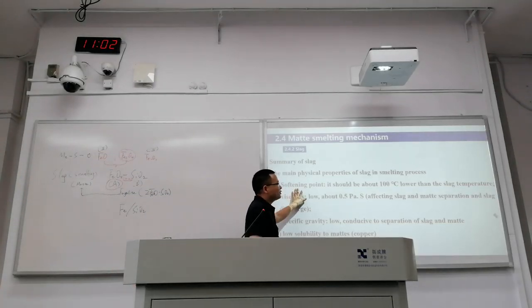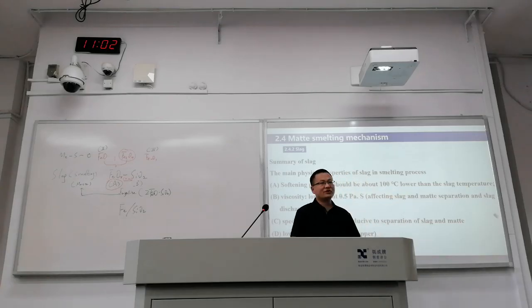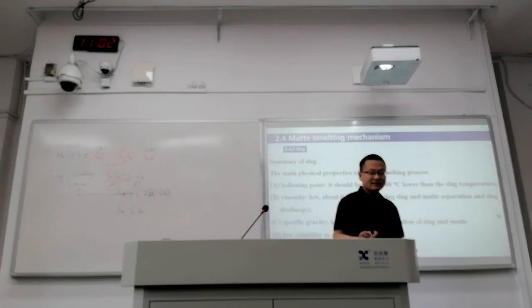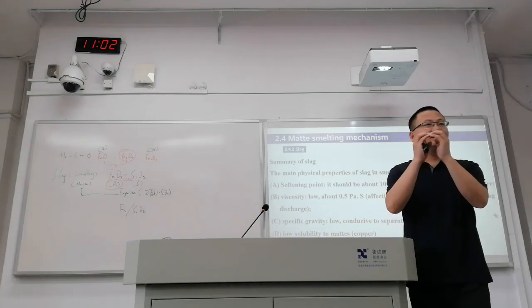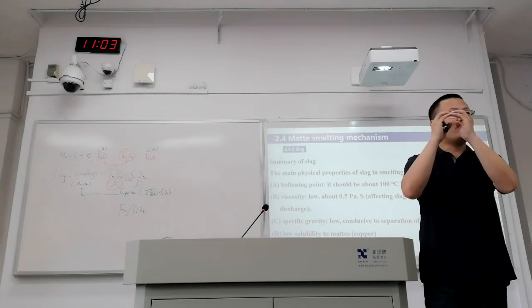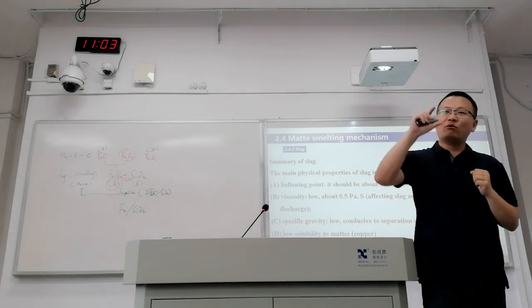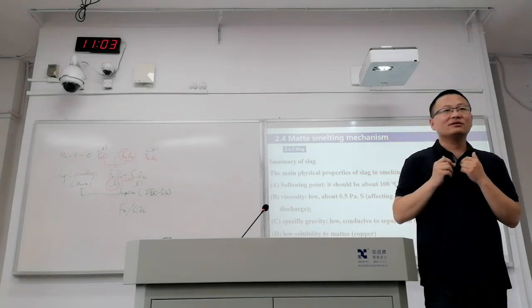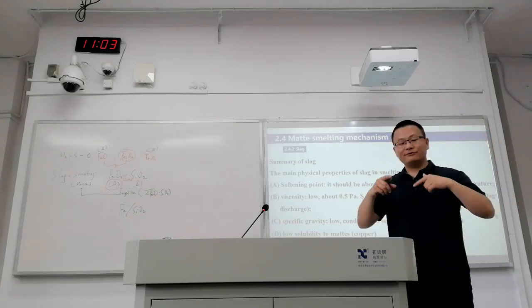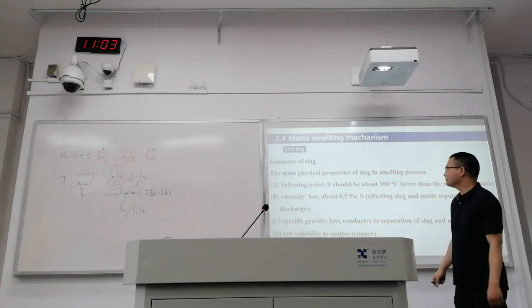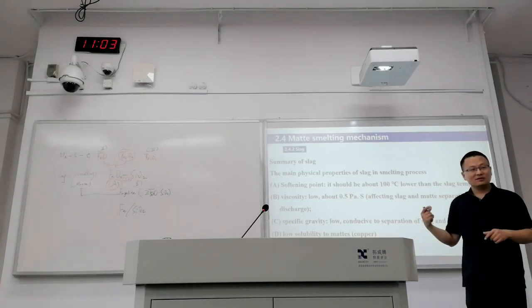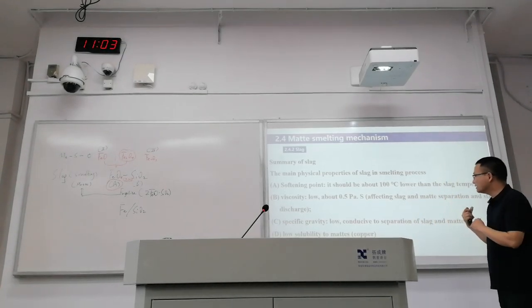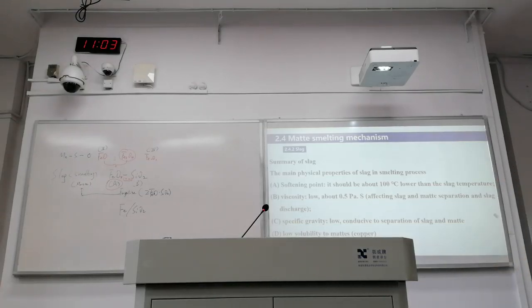So the softening temperature should be 100 lower than the furnace temperature. What does it mean? When we are having some slag, the softening temperature is 1100, and we are running the furnace at 1200. So we have a 100 safety range that keeps the slag fully melted. And the viscosity should look like the video you have already seen, so it should flow nicely. And the gravity should be smaller, which is easier for the separation of the slag and mat.